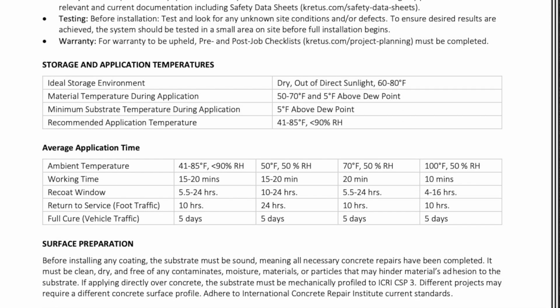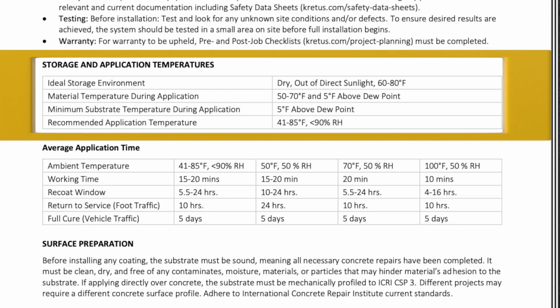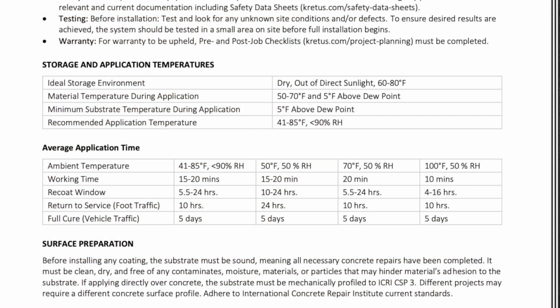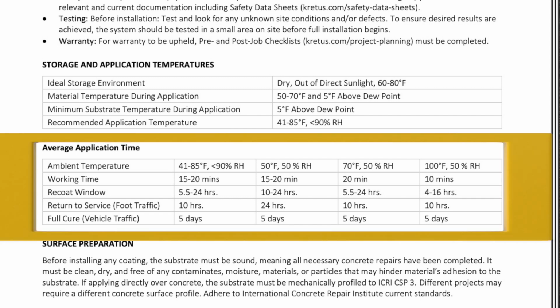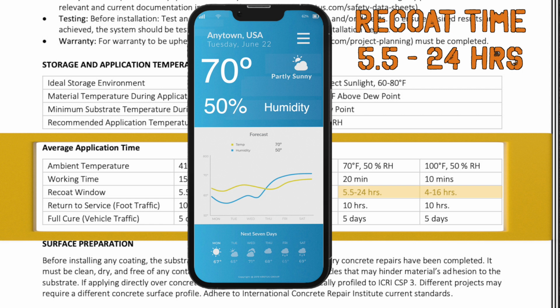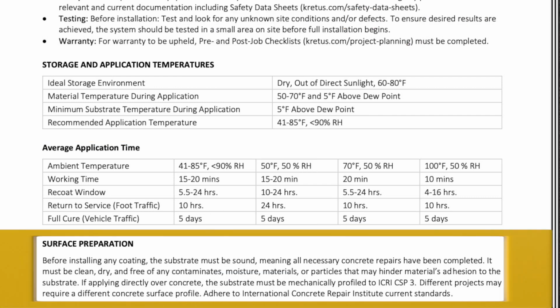There is information on storage and application temperatures. The ideal storage environment is dry, out of direct sunlight, between 60 and 80 degrees Fahrenheit. There is a chart with average application times specific to ambient temperatures. For example, if the ambient temperature at the time of application is 70 degrees Fahrenheit with 50% relative humidity, the working time will be 20 minutes. Recoat at 5.5 to 24 hours, return to service at 10 hours, and full cure or forklift traffic at 5 days. Finally, there is a reminder about surface preparation.